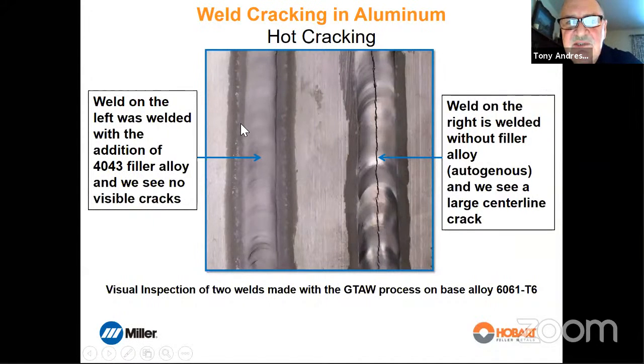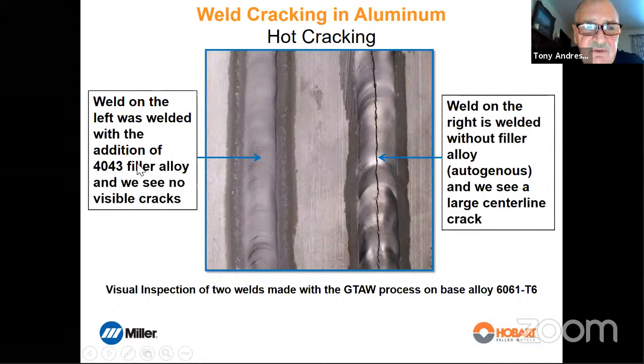This is a piece of 6061. The weld on the right was autogenous, no filler material. You can take a TIG torch, take a piece of 6061, put a real heavy bead down the plate with no filler alloy, and I'll guarantee it will crack. Same plate, same welding process, 4043, or any filler metal for that, 4043, 4943, 5356. 4043 is a good example. Add some filler alloy, no cracks, same base material.